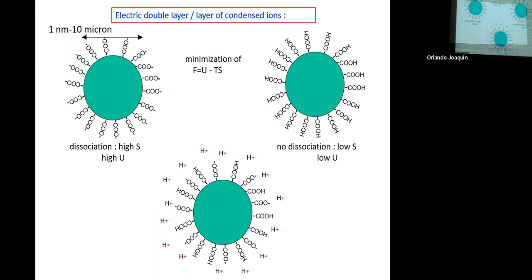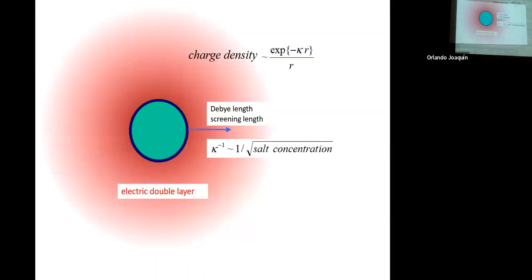What happens is something in between: you have a plus ion which dissociates from this group, but it doesn't disappear to infinity. It's attracted by the negative surface and forms a kind of positive cloud around this particle, which is called an electric double layer. So we have, for example, a negatively charged colloidal surface, and an H plus ion, forming a cloud of positive charge around the negatively charged colloid, with an extent called the Debye length or Debye screening length.